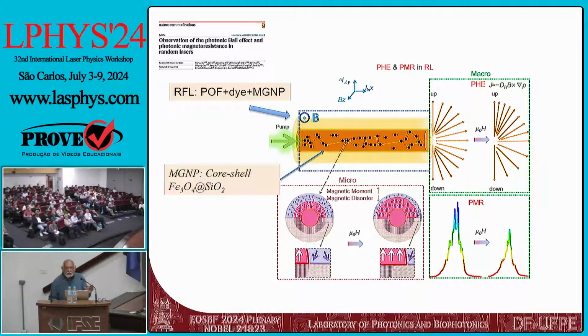We use the polymer optical fiber with magnetic nanoparticles. They are core-shell nanoparticles, silica around and ferrite in the core. They are very small, nanometer size. In one measurement, we look directly at the fluorescence for the photonic magnetoresistance. We see this decreasing as we increase the magnetic field. But for the experiment to see the photonic Hall effect, you have to look transversely.